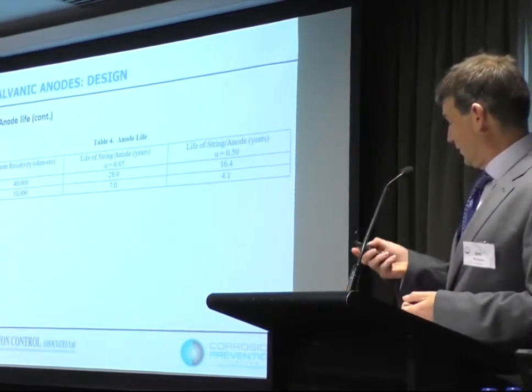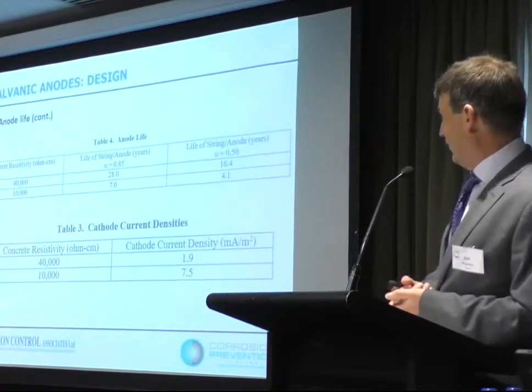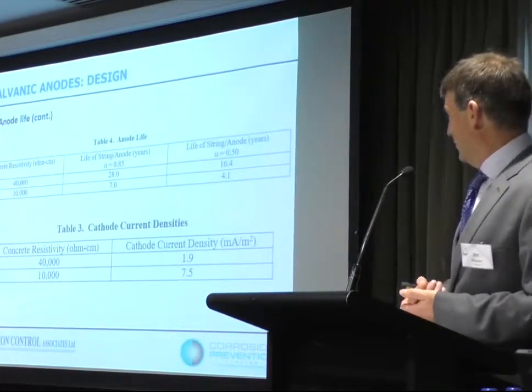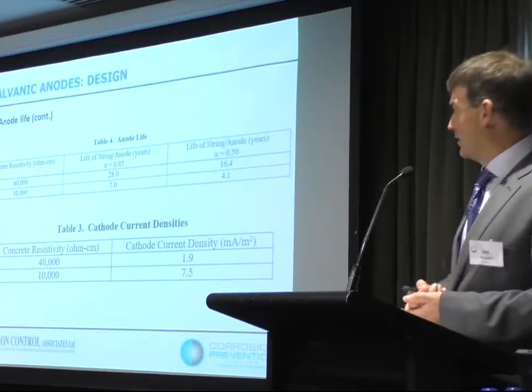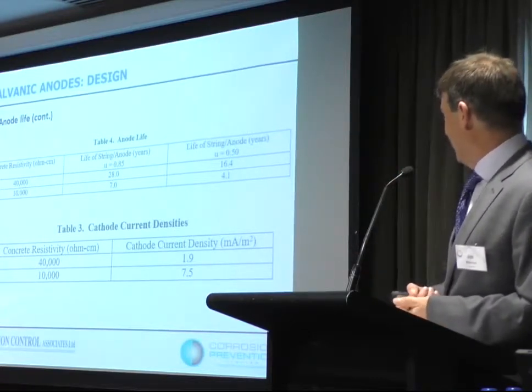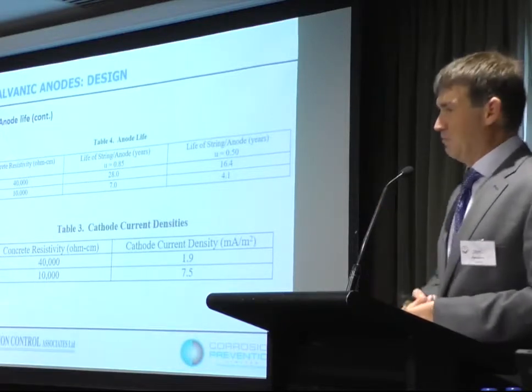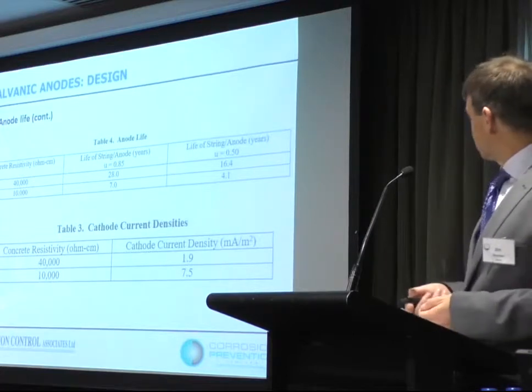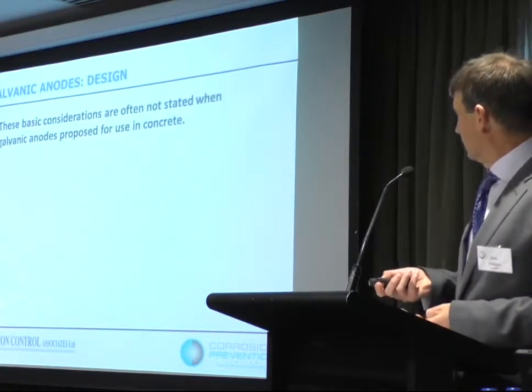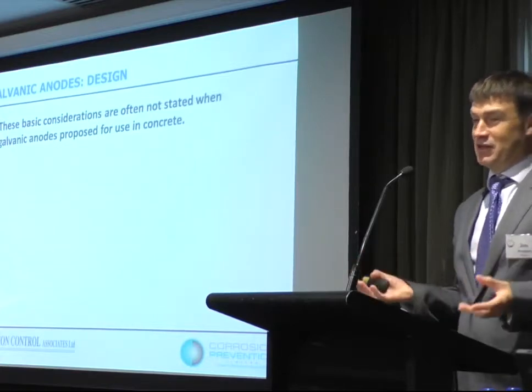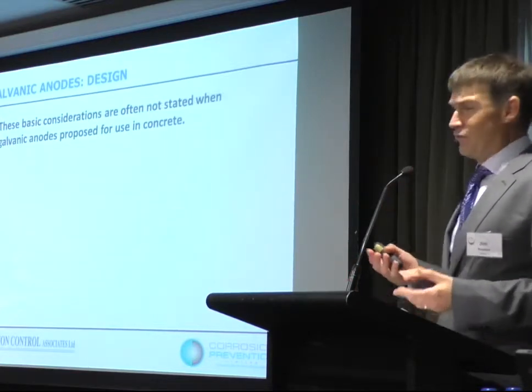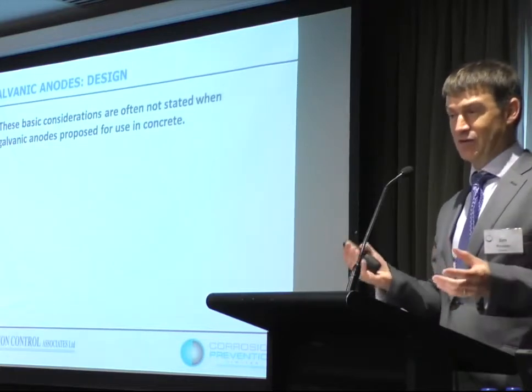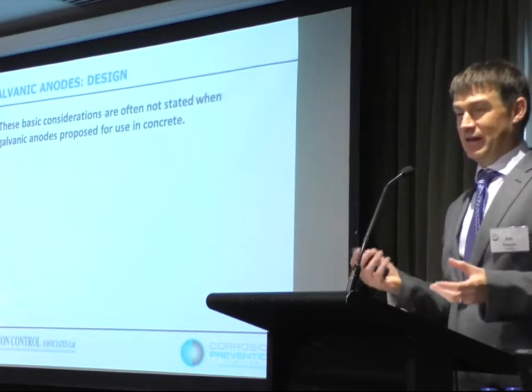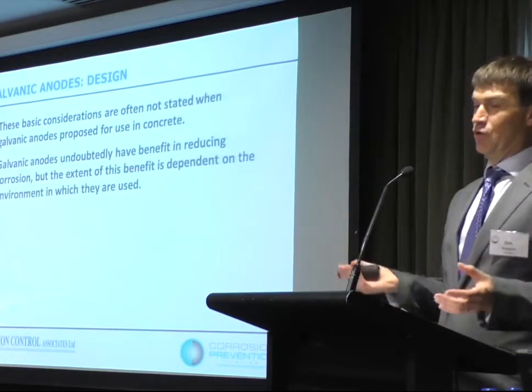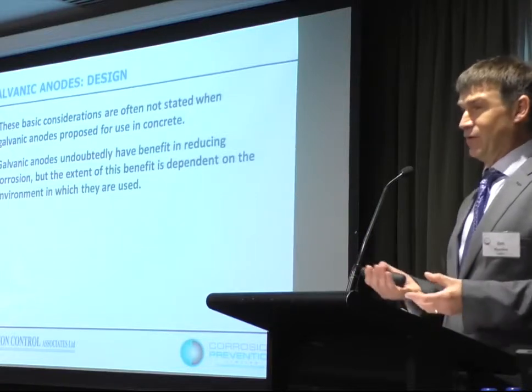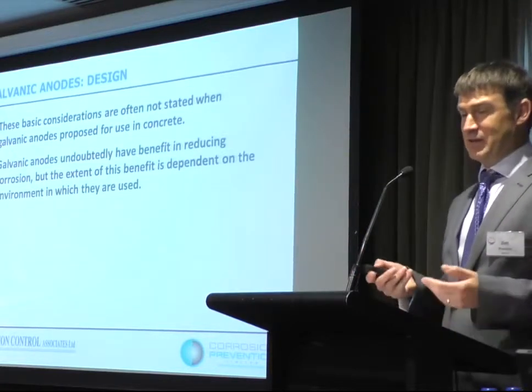What if it's less? So if we compare it to our cathode current densities, well, our 40,000 ohm centimeter concrete, we're not getting much current, but it's going to last a reasonable amount of time. Our 10,000 ohm resistivity concrete, we're getting a better current density, but 7 years. And we flag this up because really these basic considerations for galvanic anodes, they're often not stated. You know, it's maybe not clear to a purchaser or a client what it is they're getting. For sure, they're going to do some good, but the benefit or the extent of that really needs to be determined.